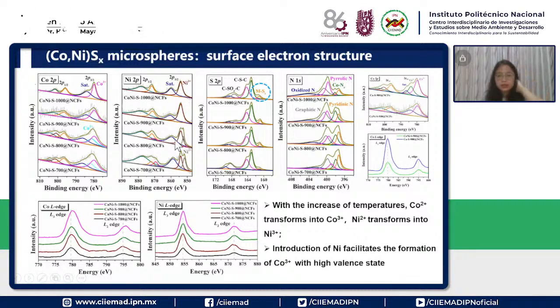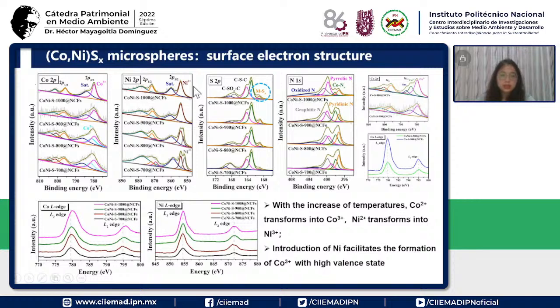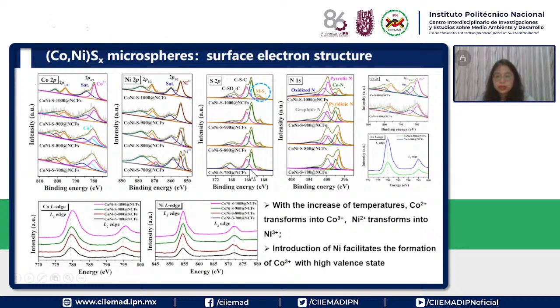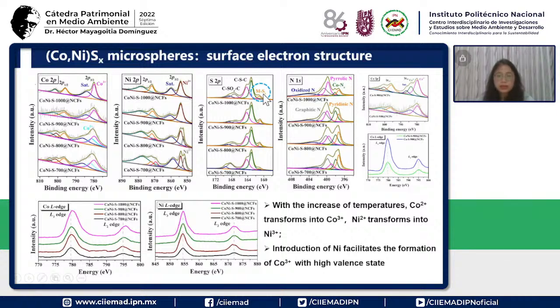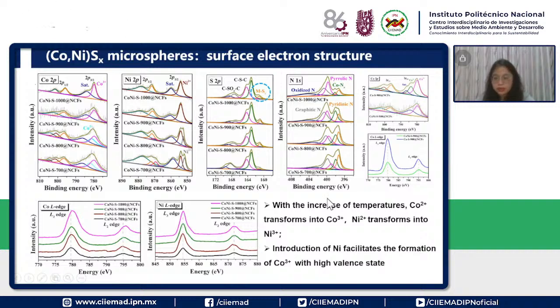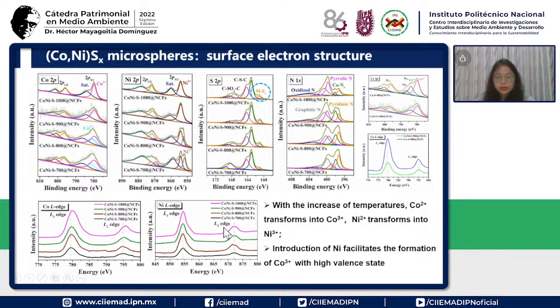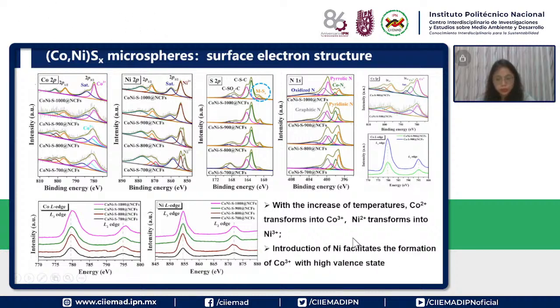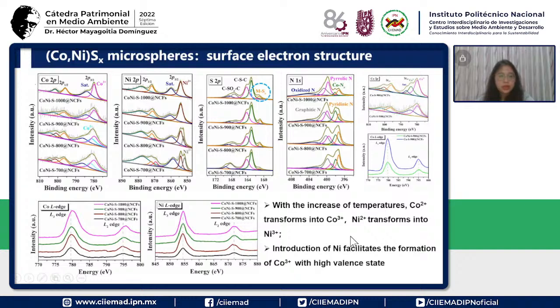For the nickel, it shows a similar situation. At the lower temperature it is also nickel 2+ and nickel 3+, but when the temperature increased to 900 and 1000, it's only nickel 3+. For the sulfur, it confirms the presence of the metal connected with the sulfur. And we can say after the introduction of nickel, it facilitates the formation of cobalt 3+, which is the active site for the ORR or OER reactions.